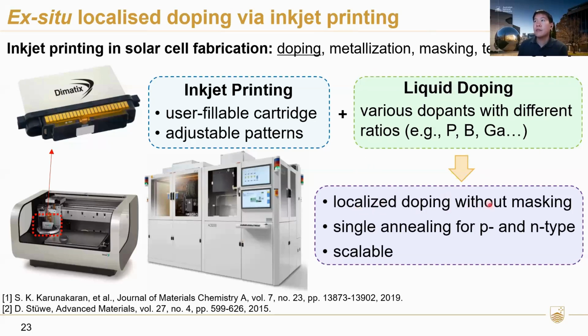In this case, what we're proposing is without a masking step or without a patterning step. And we'll show later as well, hopefully we can combine the annealing of the boron diffusion and the phosphorus diffusion together, so eliminating one of the high temperature steps for the process. And largely we believe that inkjet printing, there's a lot of interest in it in industry, not just in PV, and we believe that technology will be scalable.